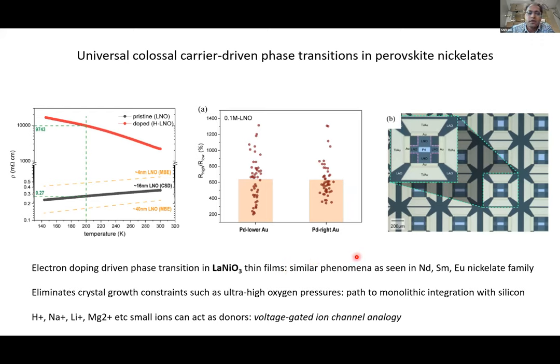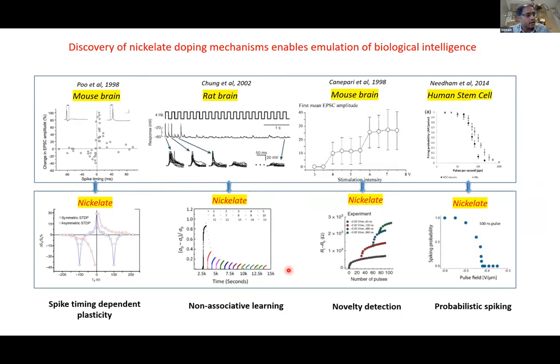And more recently, we even showed that you can grow these materials by atomic layer deposition, which is now a very important technique for mainstream semiconductors. So you can sort of expand the reach of these exotic materials into semiconductor systems, semiconductor platforms. And also, I don't have data here to show, but I have the data, I've not put it on these slides, we can extend the electron doping strategy from protons to other elements like sodium, lithium, magnesium, and so forth. So in other words, you can sort of slowly work towards voltage-gated ion channel analogies that are from standard neuroscience studies. So this is my last slide, I think.